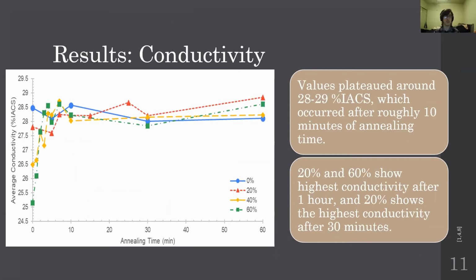This could be a result of an error in the machine, or just an experimental issue in some other way, but it could also be something to do with the structure itself, whether or not the dislocations have aligned themselves in a way that allows electrons to move, or if there's a solid solution where copper and zinc split apart a little bit, that gives a location where electrons flow more freely. This information, while it does revert to our original numbers, it does raise some questions as to why they're higher. We would expect them to be lower.